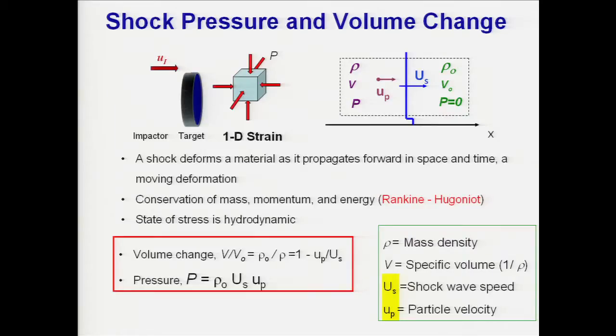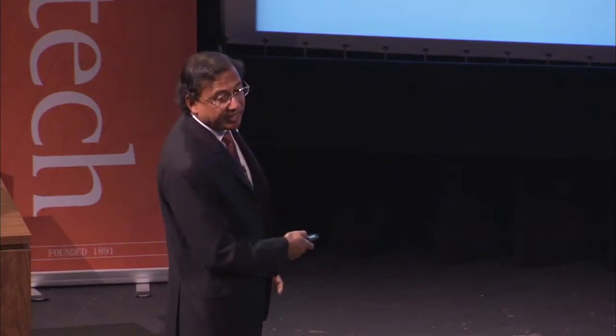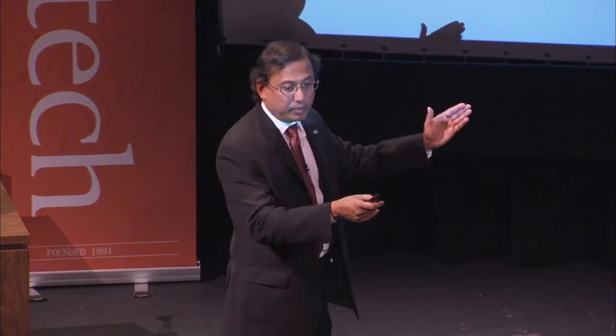And similarly, from the conservation of momentum, the pressure is given by the product of the density, which we know very well, the shock wave speed, and the particle velocity. If we can measure the shock wave speed and the particle velocity, then we will know the pressure. So that is the way you characterize the material. The two quantities of interest are the shock wave speed, how fast the shock is moving, and the particle velocity, how the mass is set in motion. In the symmetric impact, if the impactor and the target are made of the same material, then the particle velocity is simply the impact velocity divided by 2. This is from the equipartition of the momentum.